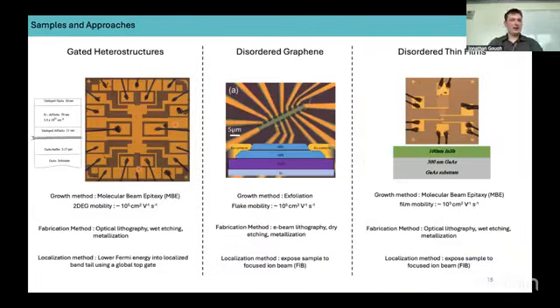So we look at a variety of samples and a variety of methods to study strong localization. The first is in gated heterostructures. These are typically relatively high mobility 2DEGs, so 2D electron gases. And then by applying a large voltage to a gate some distance away, separated by a dielectric, you can deplete carriers from the 2D system, which then lowers your Fermi energy into this localized band tail.